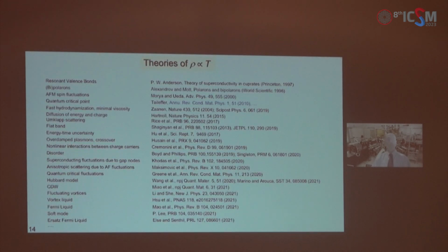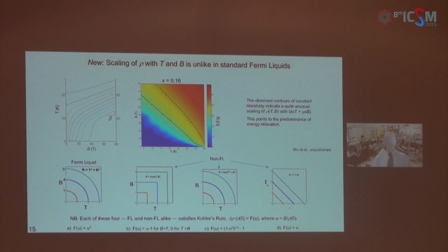And that's of course hard to reconcile with Fermi liquid physics, and this indeed was recognized by all leading scientists in the field, though many of them proposed various explanations, one more exotic than the other. But so far, I don't think there is a clear winner, and certainly there is no consensus. So it seems fair to say that this problem is still fully open. Now, we can learn more from the magnetoresistance, and in particular from scaling. By scaling, we can reveal a hidden symmetry in the data.